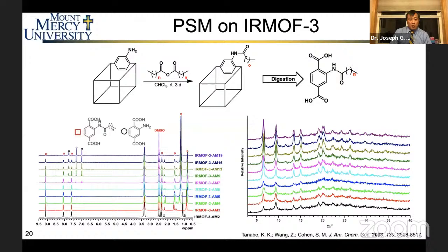And so what's really unique here is when you look at the longer chains, notice that the conversion wasn't as high, which, as I said, they were just kind of showing proof of concept. But if you have 19 extra carbons or 16 extra carbons, there's a couple of reasons why that's going to be. Those are longer. It could be blocking the compound from coming in, but most likely those carbons are so long that it's really hard for it to stay inside the cavity and do a reaction and stay put there.